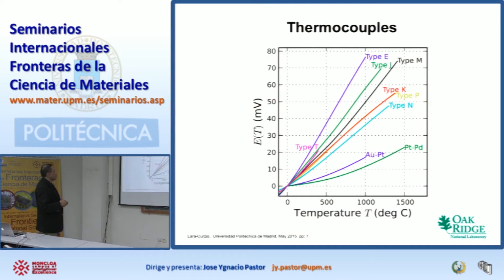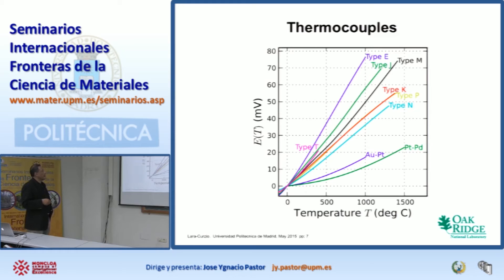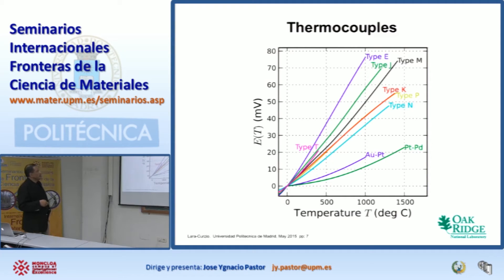This is the voltage measured with thermocouples: a plot showing voltage in millivolts from 0 to 80, and temperatures in degrees Celsius from 0 to 1,500°C, for different types of thermocouples. In the lab we use type K a lot — you can safely use type K up to about 1,000°C. These are fairly robust thermocouples. What you want in a thermocouple is a large slope in this curve, so it gives you more voltage per degree of temperature and more precision in your measurements.